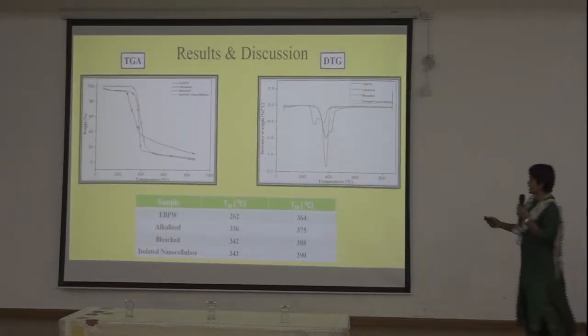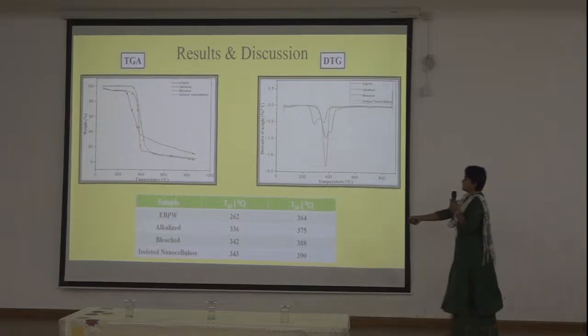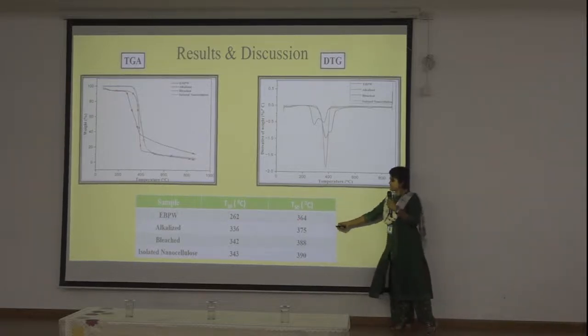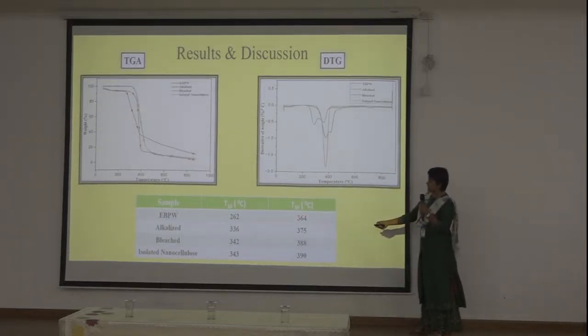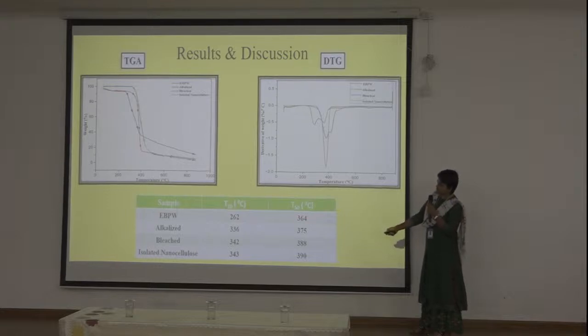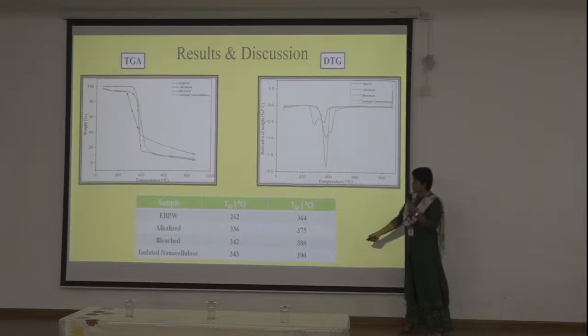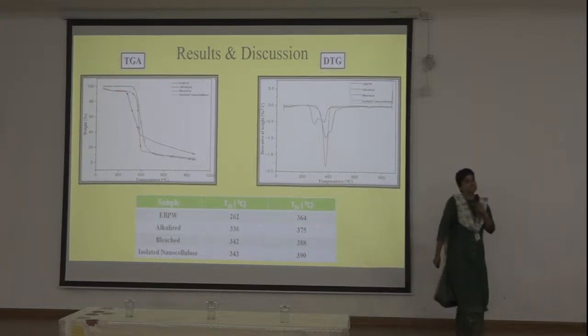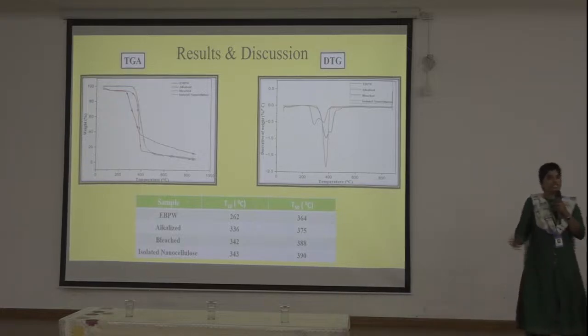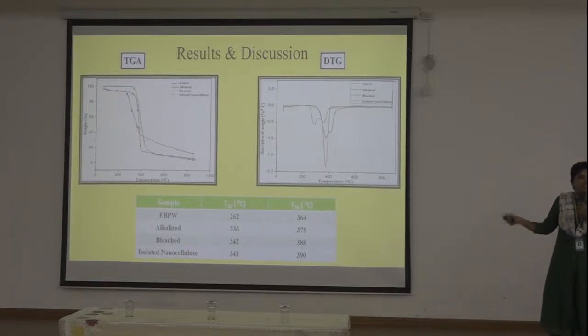TGA was done. Here you can see that for the raw material, 50% weight was lost at 364 degrees, whereas for the isolated nanocellulose, 50% weight loss occurred at 390 degrees. This shows that the isolated nanocellulose is thermally more stable compared to the raw material.